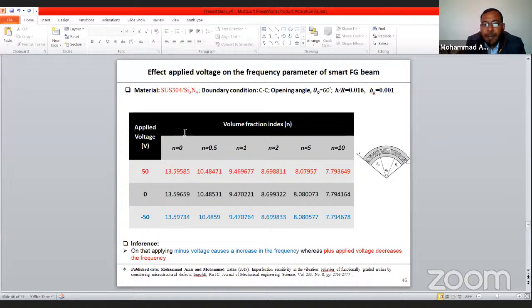And here the effect of applied voltage on the frequency parameters of the functionally graded beam is observed. Three potential differences are taken, applied voltage: 50 volt, 0 volt and minus 50 volt, for various volume fraction index n equal to 0, 0.5 and 10. Here we observed that when no voltage is applied, meaning V is equal to 0, then it has some frequency, and when we apply minus voltage, then the frequency parameter will increase. And in case of application of plus 50 volt, the frequency parameter decreases.